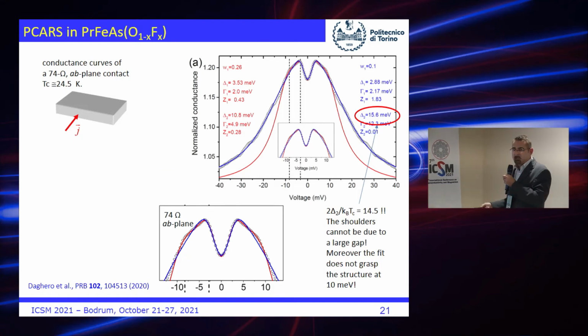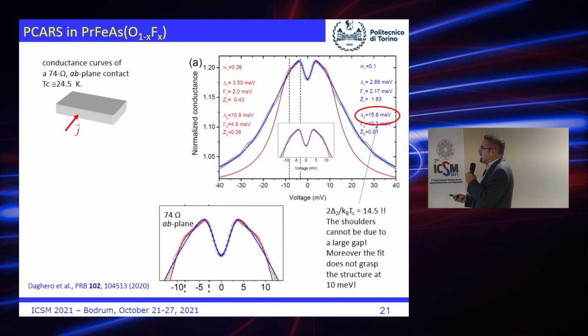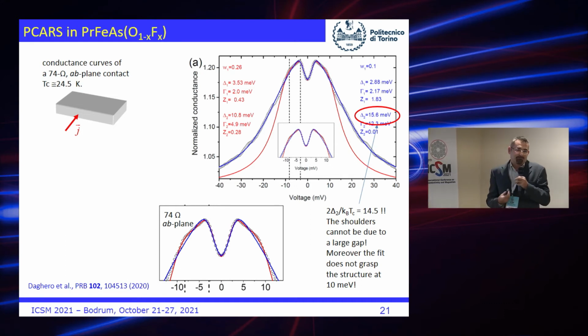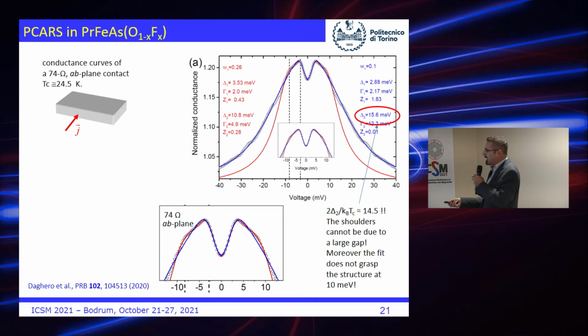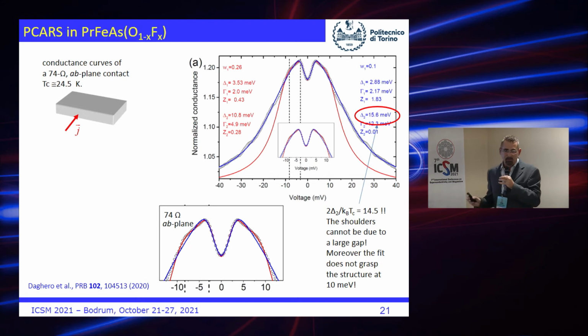Okay. Now, we have other spectra. If you try to fit the spectra, this is a spectrum rather nice, okay? You can try to fit the whole spectrum, including these wide shoulders, but what happens? First, the gap you obtain is 15.6. Incredible. 2 delta over kTc of the order of 15 is incredible. So this is a first hint that this may not be a gap.